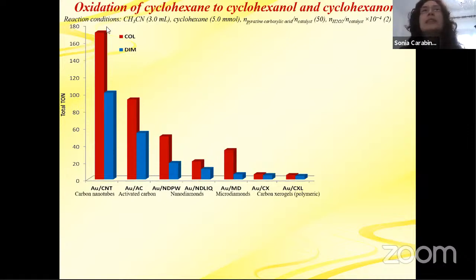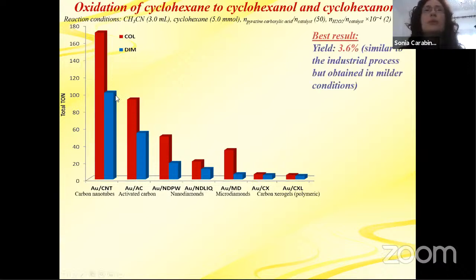So we have the results here, and we see that the best results were obtained with carbon nanotubes, and the yield was 3.6%, which is similar to the industrial process that was 4%, but obtained in milder conditions, which was room temperature and 6 hours. Remember that the industrial process needed 150 degrees. And here it was room temperature, and just 6 hours we obtained a yield very similar, shall we say.